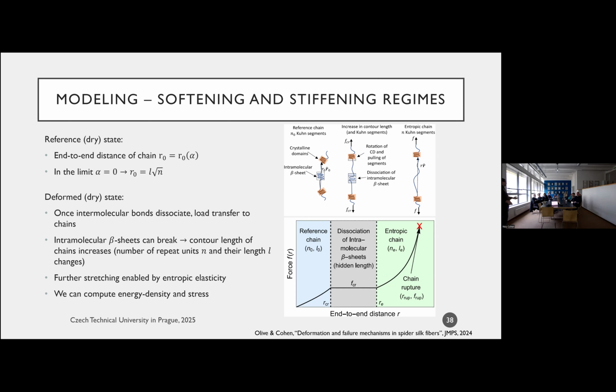Inside the chain, there's some evidence. There were papers that reported that there are intramolecular beta sheets. So these are structures that are much weaker. It's a beta sheet, but it's kind of like having a string and you rope it around itself and you interconnect them with a very soft bond. And once the intermolecular bonds break, these chains begin to feel a very strong stretch, very strong force. Because of this force, this structure breaks and the chain elongates, right? So we get this elongation.